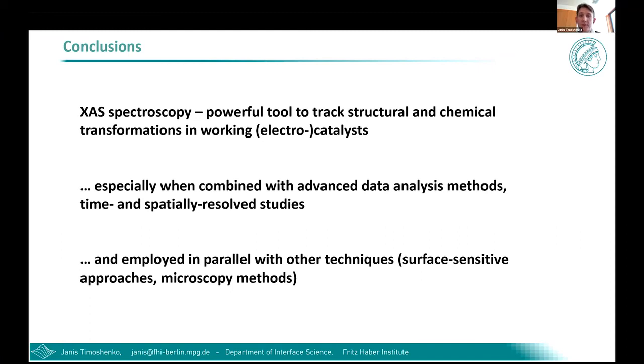Right, yeah, that's an important limitation. I briefly mentioned in my talk that, as any other spectroscopic method, it gives you the average picture, which is a limitation, of course, because if your sample is complicated, which it normally is, so it has a mixture of different species coexisting, you need to account for that in your analysis. On the other hand, it also gives you maybe a more honest overview of what's happening with your sample. You don't focus on one particular small region in your sample, but you get information about the entire catalyst and see how it can be correlated with its catalytic performance.